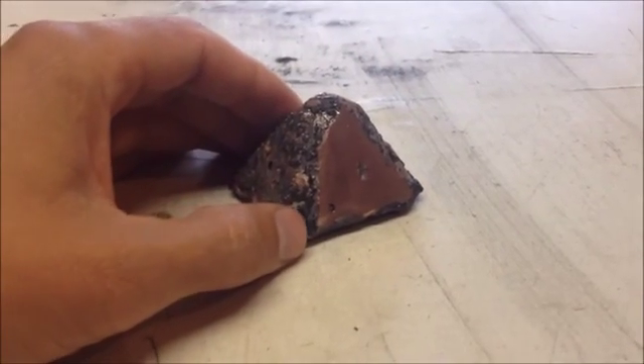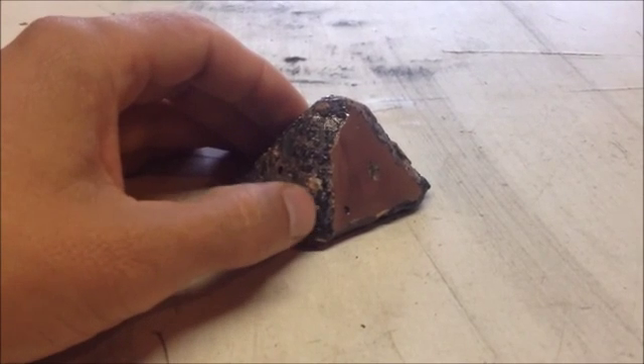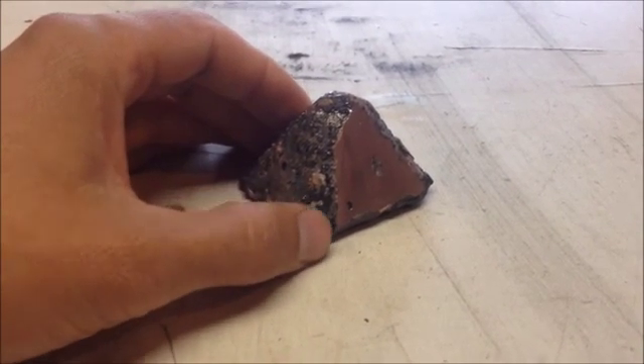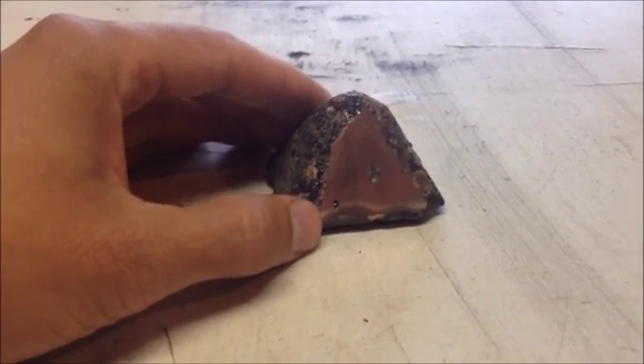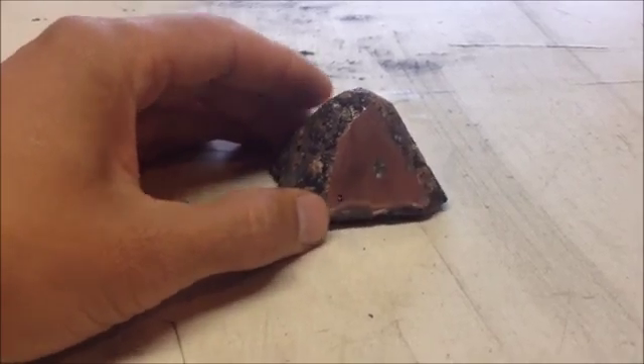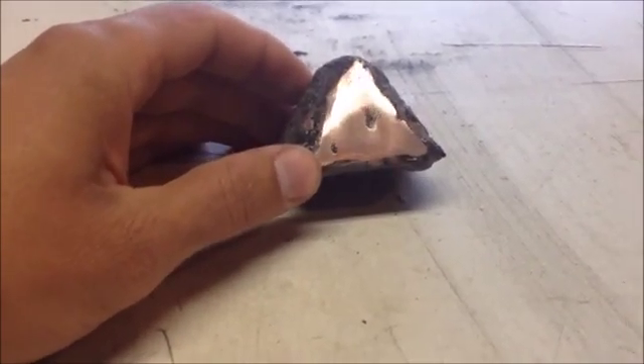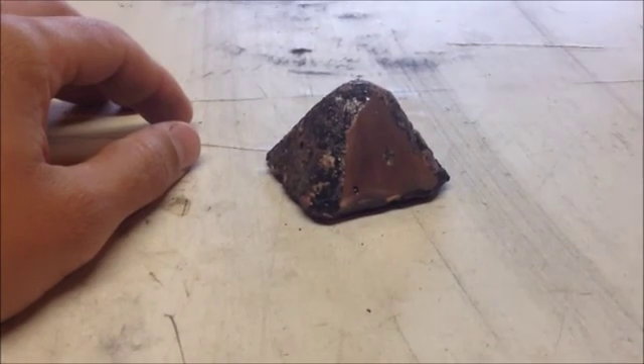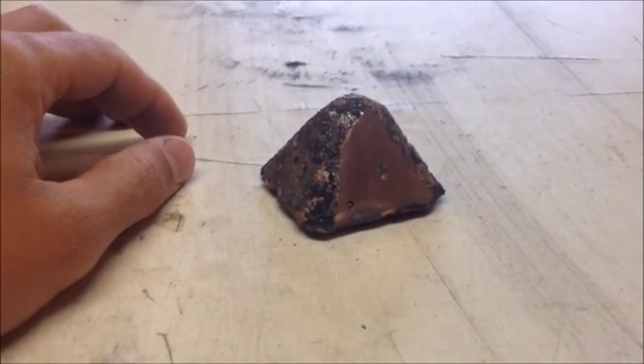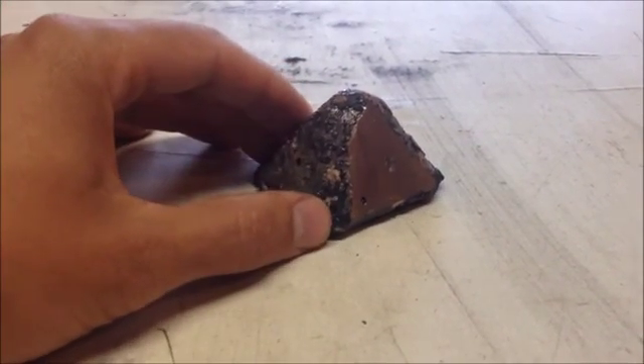So by doing the math with the results of the XRF gun, I can calculate the amount of gold that we recovered. And we recovered right about 8 grams of gold by doing our copper collector metal smelt on the number 1 and number 2 table concentrates.